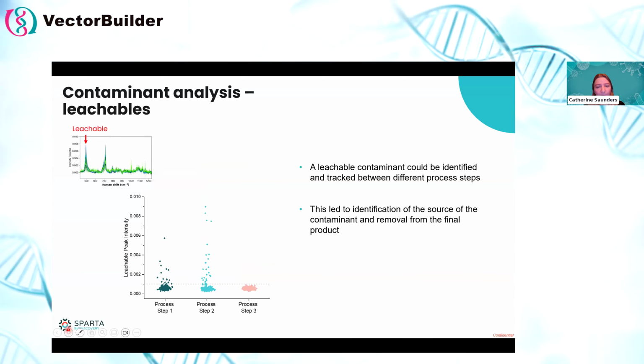So that is biological contaminants. And another type of particulate which can be present in the samples is plastic particles and leachables. So actually what we found was in these same EV samples, we could detect small plastic particles. And these are leachables which can be introduced during the production process, ironically during some of the purification steps. And now, because the Raman spectroscopy is chemically specific, we could detect not only the presence of these particles, but we could also chemically identify them to this specific plastic and identify the source of these. And so having really this deep understanding of the formulation and tracking these leachables, what process step they were introduced in, it also led to a bit of tweaking of the purification process and eventually, their removal in the final product, which was a great result for our collaborators.